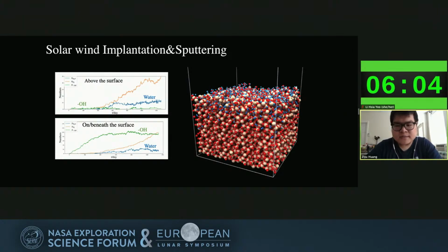When we convert it to a 60 micrometer dust, the OH and H2O abundance is less than 1 ppm. But it shows that incoming solar wind hydrogen atoms can combine with hydroxyl and then form water molecules, although it's very unstable and easily sputtered. Another interesting thing we found is that although the hydrogen molecule H2 number is still growing, the number of hydroxyl and also water molecules are becoming stable. So this indicates that the surface will be saturated with hydroxyl and water molecules if the implantation continues. And the saturation time we found is about 400 days based on the solar wind conditions and local temperature.